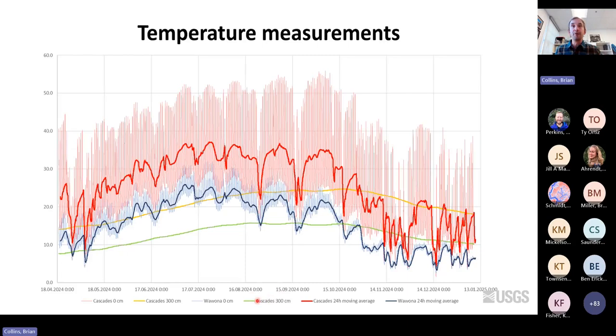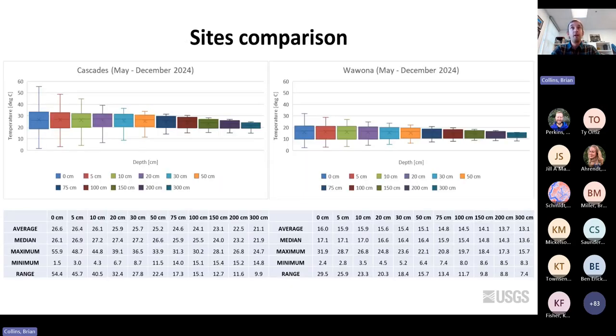In green it should be Wawona, not Cascade. So you can see already that there are big differences between the 2 sites, even in the amplitude or in the absolute temperature. When we compare the 2 sites, you can notice the big differences in the south-facing side, where the average temperature on the surface from May to December was almost 27 degrees, with a temperature range of almost 55 degrees, and a maximum of 56 degrees on the surface.